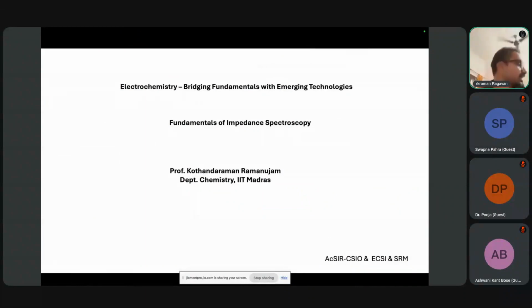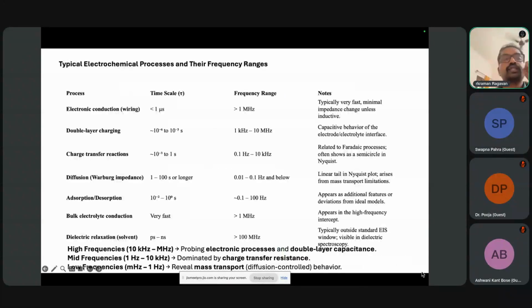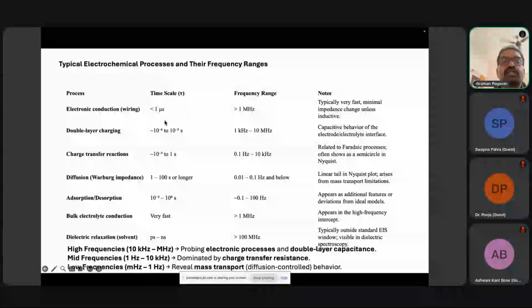So now if you can see in this table, I have listed several processes here. For example, electronic conduction that is happening within the electrode or the solid electrodes and the current collectors and so on. So these will respond in a time scale of less than 1 microsecond. That means their frequency range will be above 1 megahertz. Typically, we don't have the instrument in our laboratory. The common potentiostat, galvanostat that we use does not go beyond 1 megahertz. Okay, so we cannot see this so well.